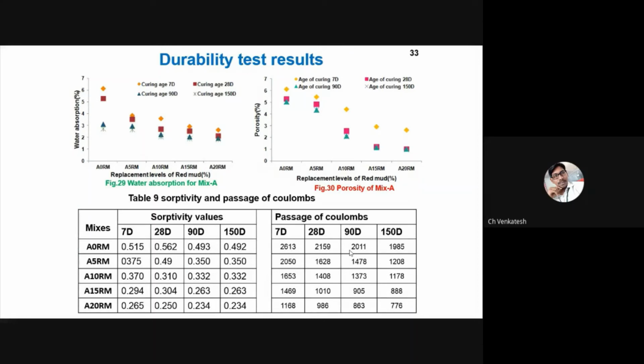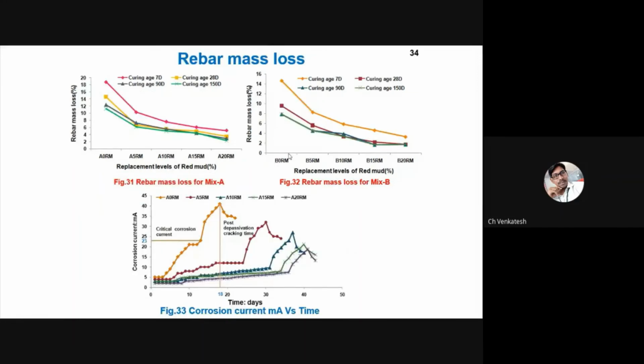The reason is that most of the red mud particles occupy the concrete pore structure, so that it becomes a seal to the concrete, so that no external agents are entering into the concrete. So this is the reason for developing good durability properties. In corrosion also, the mass loss is reduced with increase. Here we can measure the corrosion in two ways: one is up to crack observed, or up to mass loss. In both cases, a similar trend was observed.